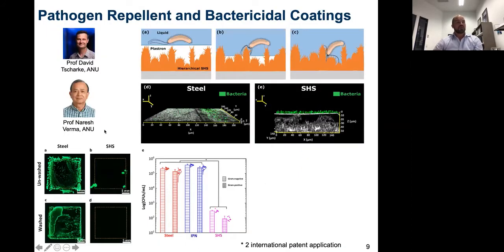But one of the first market sectors we're going to go after is actually antiviral. These surfaces are antiviral and pathogen resistant. So if we look at bacteria, we all know about the rise of antibiotic resistant bacteria, superbugs, which has the potential to, in the future, represent another pandemic if our antibiotics start to fail against bacterial strains. And what we found is that these coatings can resist bacteria. What they actually do, this is the coating in orange here, is they form this air layer called a plastron layer, which stops the liquid phase making any contact with the surface whatsoever. So the bacteria can't colonize that surface. And you can see that here, this white line is that air layer. So the bacteria can't actually make contact with the surface.